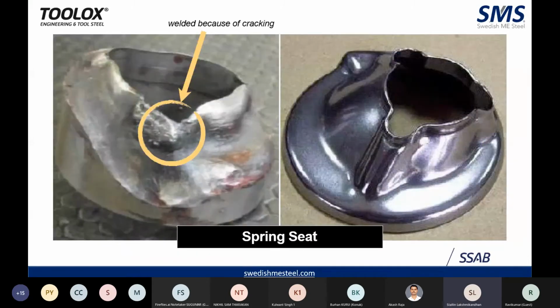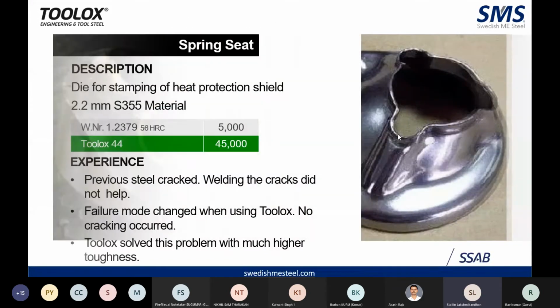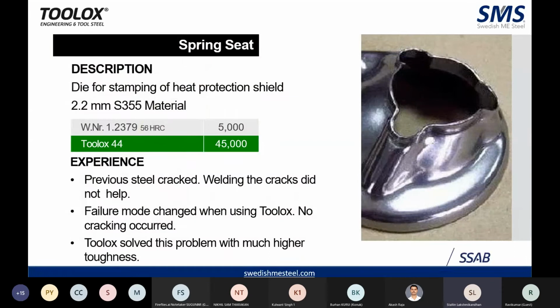And this is an area which you can attribute to Toolox much more easily. This is the area where most tool steels would not give you proper results, and you will face the issue of cracking at this juncture. Here, 2.2 mm of S355 material is being used, and the tooling has been replaced with Toolox 44. It has overcome the issue of cracking and has given good results.